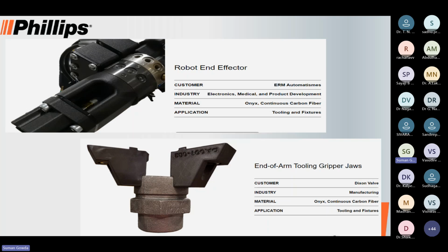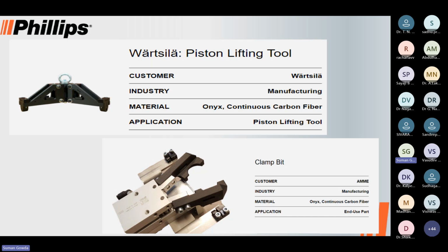Here are a few applications like robot effectors or end-of-arm tooling grippers, which were actually machined from aluminum or stainless steel parts, and are now being replaced with Onyx plus fiber combination parts. You can see a lifting tool. This lifting tool can lift a weight of close to 900 plus kgs, and a clamp bit, a regular simple clamp bit, can hold a weight of around 50 kg. The advantage here is they are using the same clamp bit. They're just changing the grippers, and it can be used for 5 different kinds of part holding. And the best thing is they can get all 5 different grippers printed overnight.